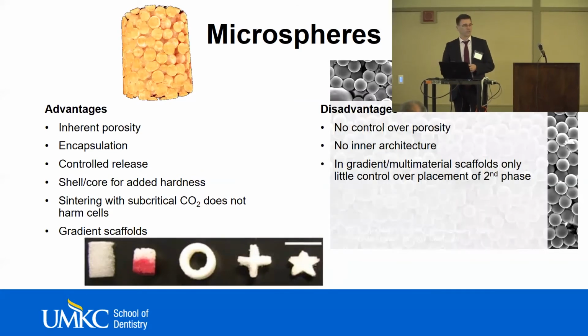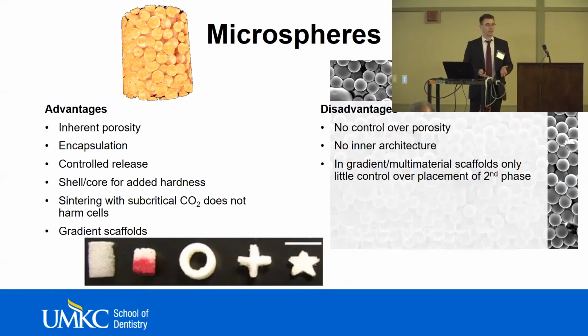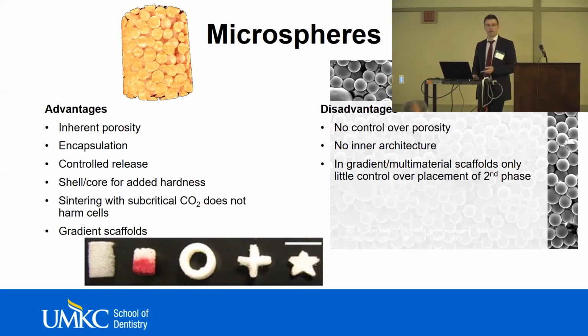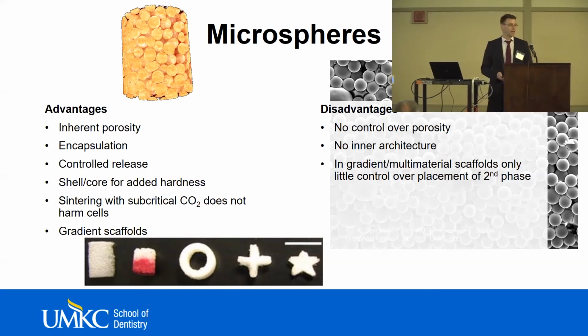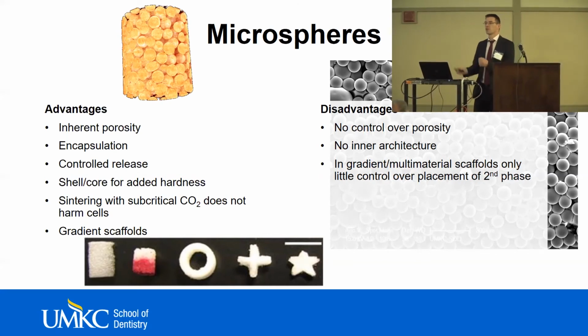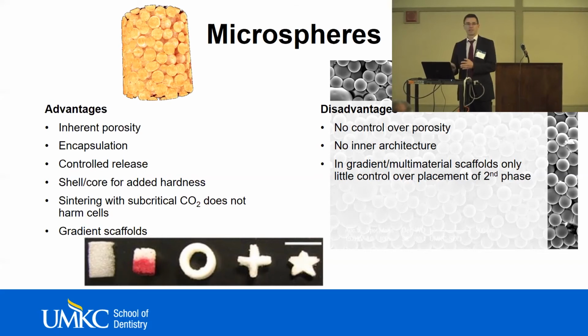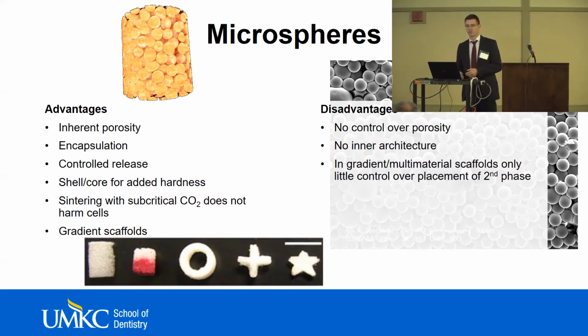However, there are also some disadvantages. We do have a porosity, however, we have no big control over it. So we cannot say where we want to have the pores, we have no control over the shape of the pores, and the size is mainly determined by the size of the microspheres. Also, we have no inner architecture, we can only choose a mold to give it an outer shape. And in gradient or multi-material scaffolds, you have only little control over the placement of the second phase. So you have a gradient, yes, but you cannot particularly place different phases at different sites within the scaffold.